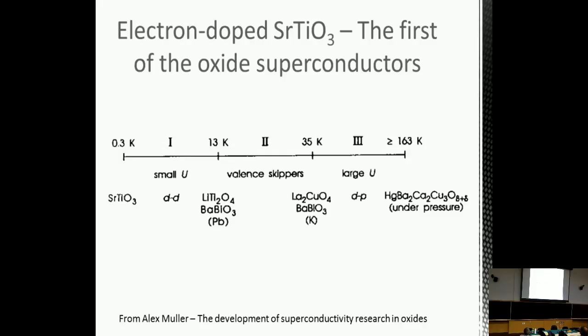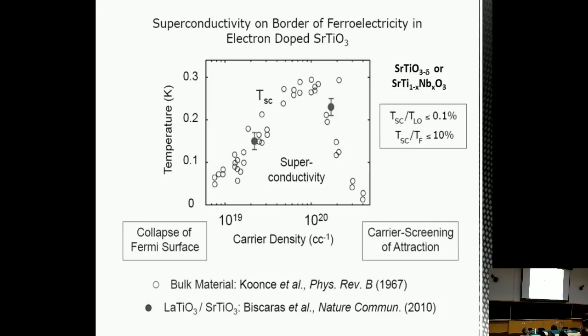But in fact, superconductivity in strontium titanate has not been understood very much right up until the present day, in a similar way to the cuprates. Of course, there's been much less attention on strontium titanate. But here we show the superconducting transition temperature versus carrier density. And we have here a dome of superconductivity. And on the left-hand side, of course, we're reaching an insulating state.